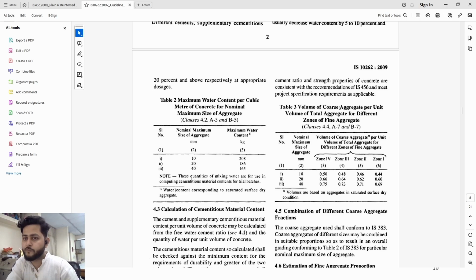And this is volume of coarse aggregate per unit volume of total aggregate, which is also called the CA by TA ratio, coarse aggregate to the total aggregate ratio. And for different zones of fine aggregate, it is mentioned: Zone 4, Zone 3, Zone 2, Zone 1. And the nominal maximum size of aggregate is also mentioned. In order to calculate the coarse aggregate to the total aggregate ratio, you need to know two values. One is the gradation of your sand and the zone in which your sand falls: Zone 3, Zone 4, Zone 2 or Zone 1. And you also need to know the nominal maximum size of aggregate in your given mix. And based on that, you'll be able to calculate.